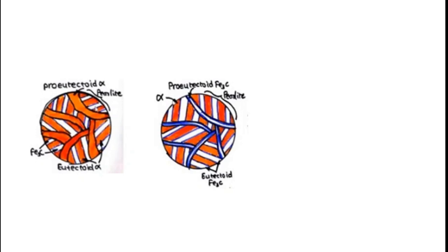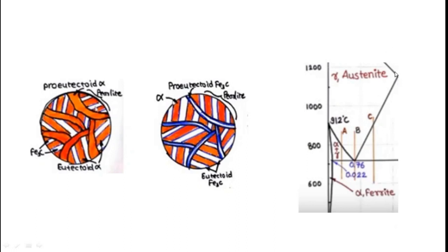The reason lies in the percentage of carbon. The hypo eutectoid zone has 0 to 0.76 weight percentage carbon, which is very close to the alpha region — alpha having 0.022 weight percentage carbon. In contrast, the hyper eutectoid zone goes up to 2.14 weight percentage carbon, and the maximum carbon on the diagram is 6.67, which defines 100% Fe3C — very far from the hyper eutectoid range.